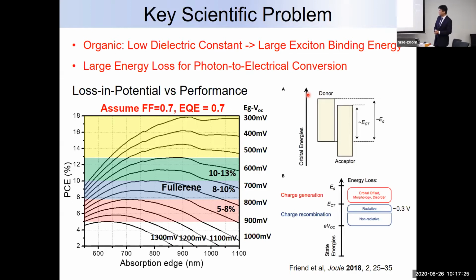For the charge generation, as I mentioned, you need to have some energy offset in order to separate the exciton. That's one of the losses. Another loss is radiative recombination, which is unavoidable. Even in inorganic material, you have around 0.3 volt of loss from that. The other one is non-radiative recombination. You try to minimize this one so that you can reduce the total energy loss. For the case of fullerene, this C60 material, usually in organic solar cells the energy loss will be in the range of 0.7 to 0.8 volt. But that sets a limit on the performance.